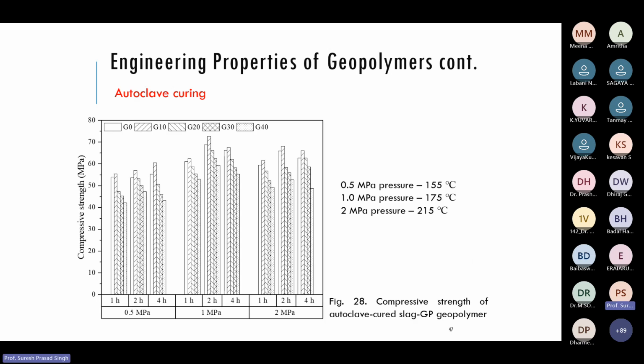Then we also tried, as usual, autoclave curing, as we do for cement. We got a strength of about 75.7 MPa in 1 hour, and in 2 hours at 1 megapascal pressure we got 72 MPa of strength, similar to cement also. If you go for accelerated curing or autoclave curing of cement, the strength in 1, 2 or 4 hours will be very high. We got similar results here.